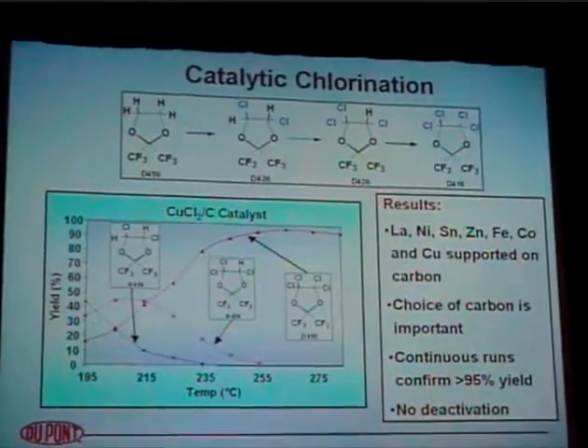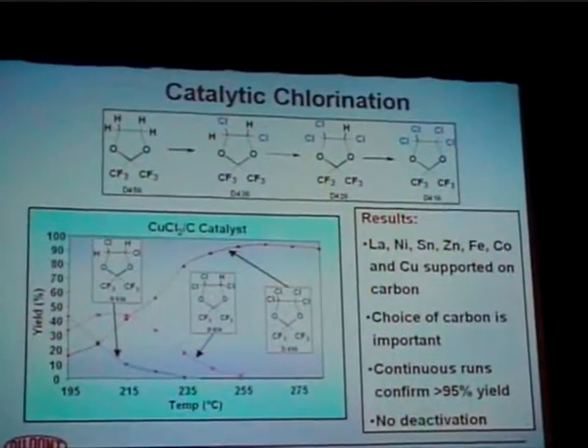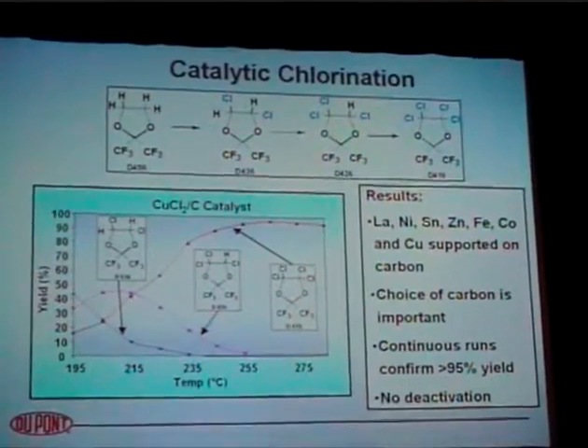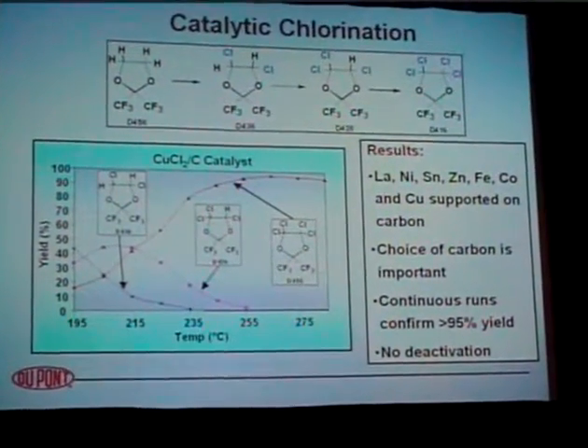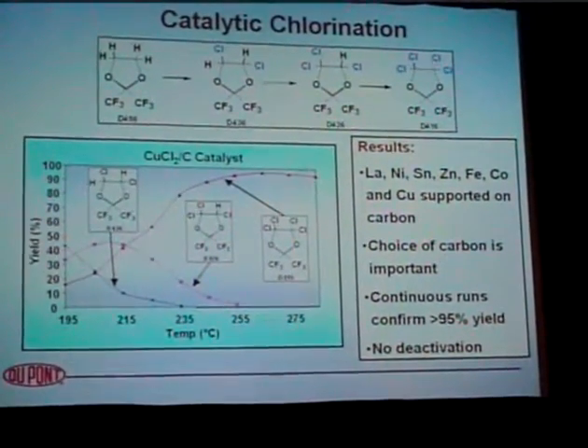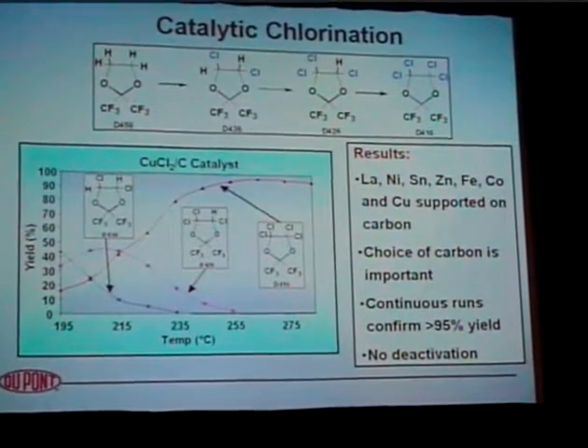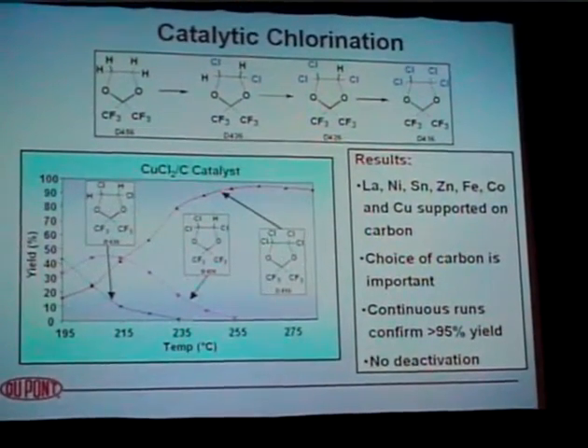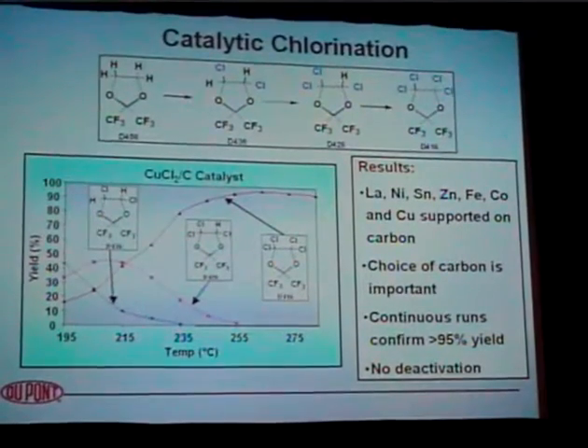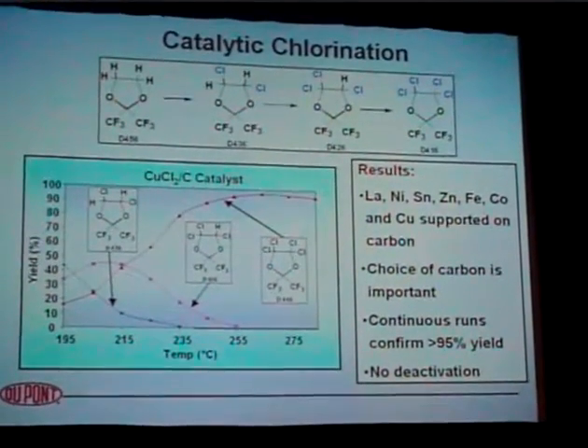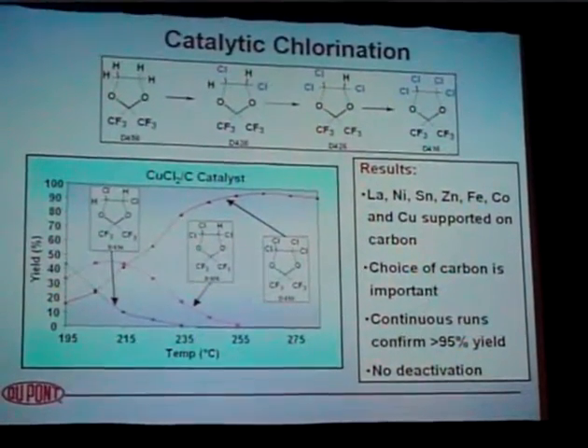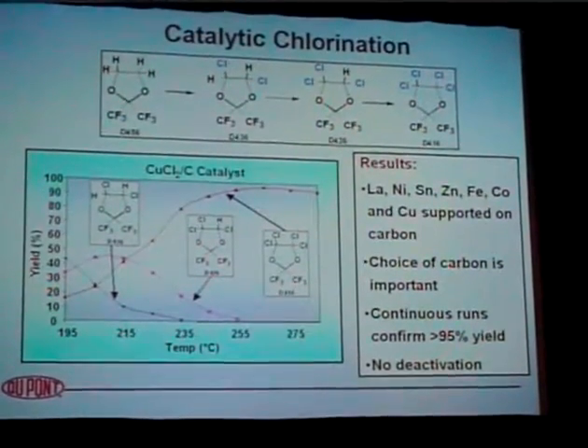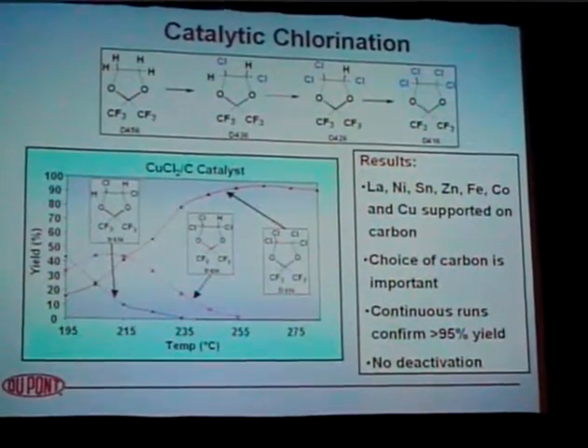Choice of the carbon, however, is extremely critical, because as I mentioned, if you're not careful, you can unzip it backwards to decompose it back to hexafluoroacetone. So carbon was important. The appropriate choice of metals on that carbon was important. And copper is one of the better metals, copper chloride on carbon for that particular reaction. So it looks like it is an excellent chlorination catalyst.